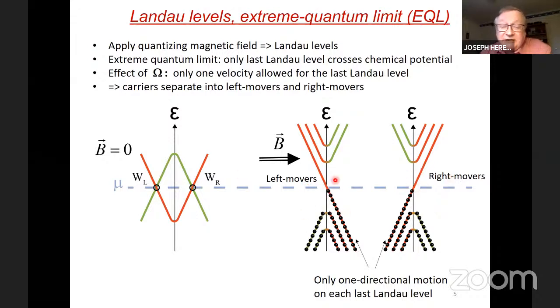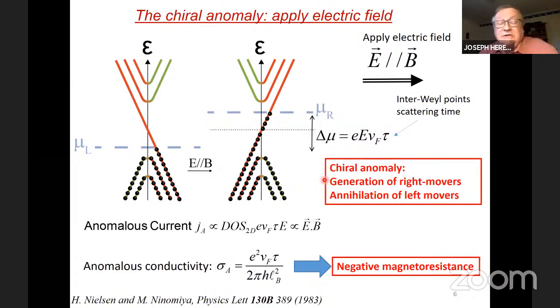We will have right movers and left movers, and their existence is a result of the chirality of the electrons at these points. Now, here is something that's actually quite well known. It's been around for many decades and has been shown to exist in many systems. It is the chiral anomaly. If we apply an electric field parallel to the magnetic field and parallel to the direction that separates the Weyl points, then in the classic picture, the electric field shifts the electron dispersion toward one direction and shifts this one also toward the same direction. But because these dispersions are linear, instead of showing this as a shift in K space, we can show this as a change in energy.